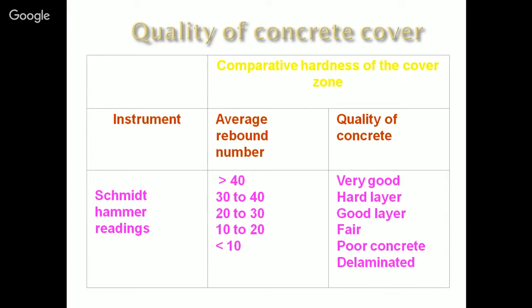So it was a very quick and easy method, by which we were able to identify the weak point in a particular casting of that concrete. It is a very suitable, commonly used, and very effective method. Depending upon the rebound number obtained, you get a reading whether the quality of the concrete is very good, hard layer, good layer, fair, or poor quality. A value lesser than 10 means the quality is very poor. It is a very easy method.